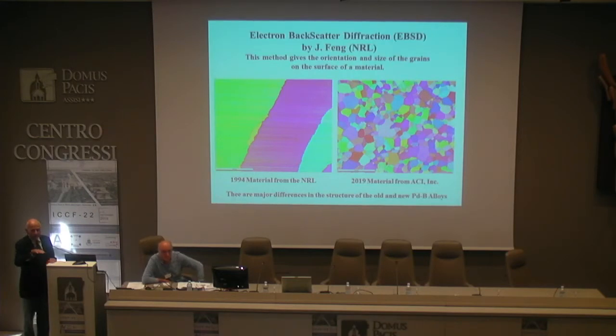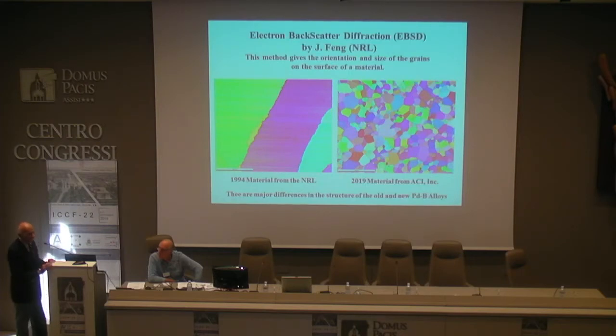So, 100, 110, 111, okay. I apologize for not saying that, but that gives you information on the grains. As many of you may know, Vittorio Violante and his team did materials analysis on this scale and then ran the materials. They found that when they had 100 faces on the surface, they were more likely to get excess heat than if they had 110 or 111 faces. So that's why we're interested in what's called the texture from a metallurgical viewpoint.